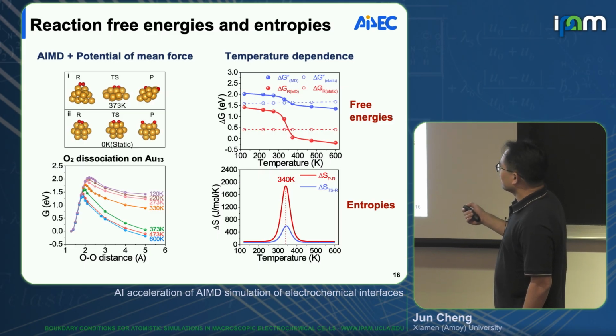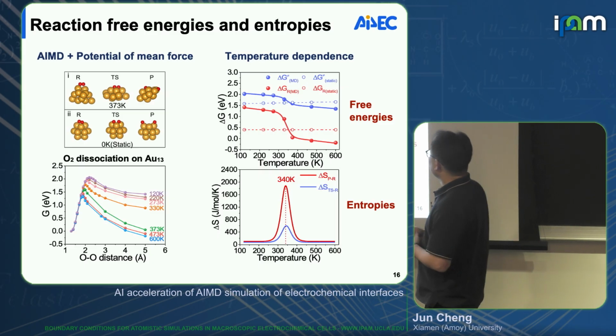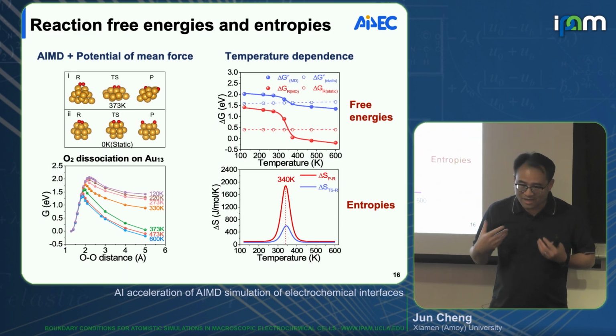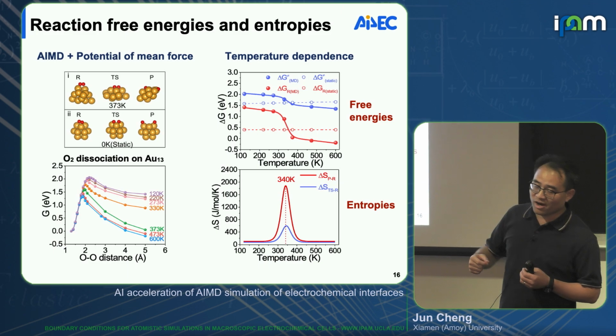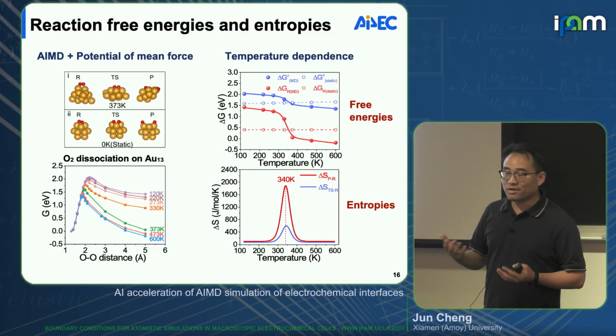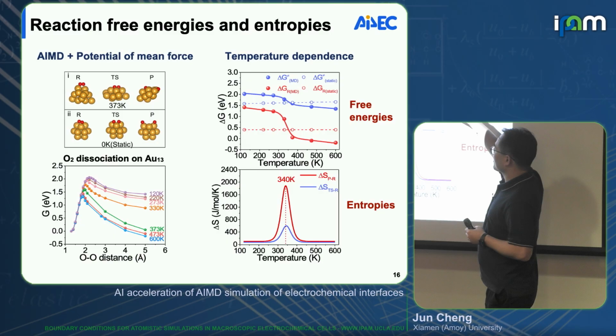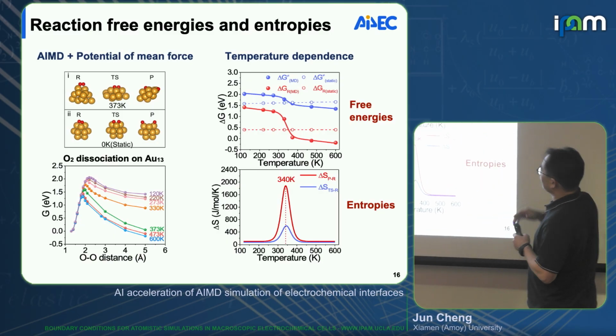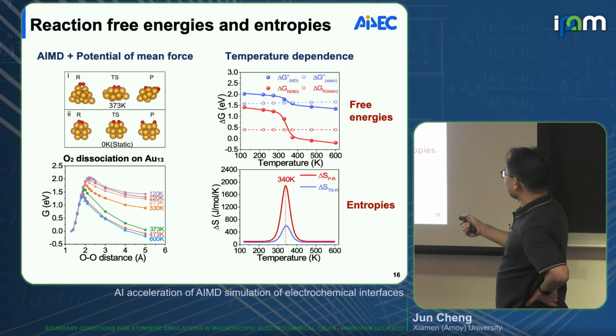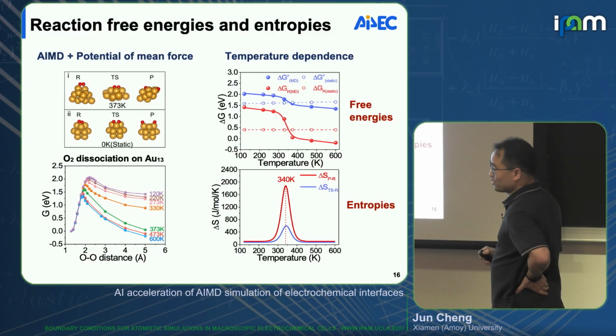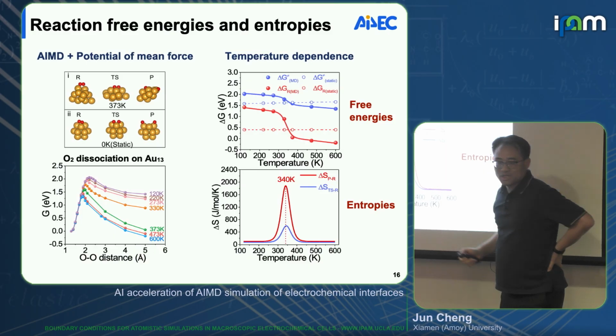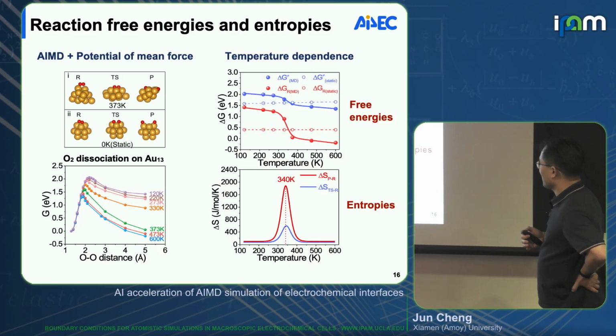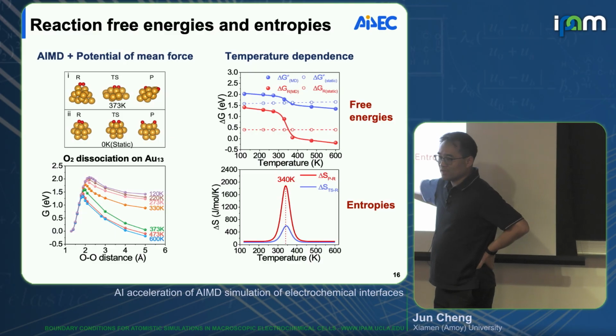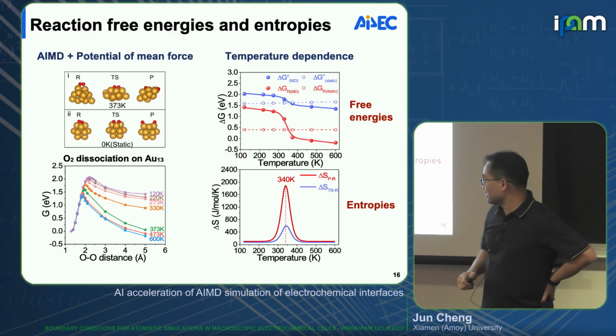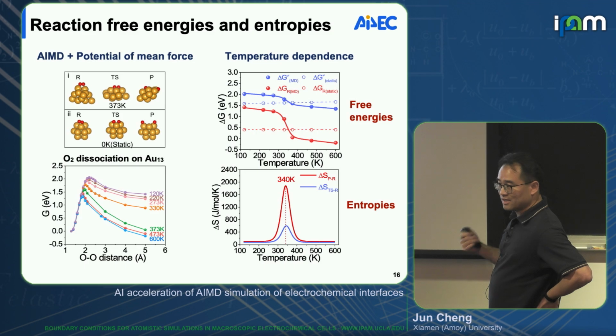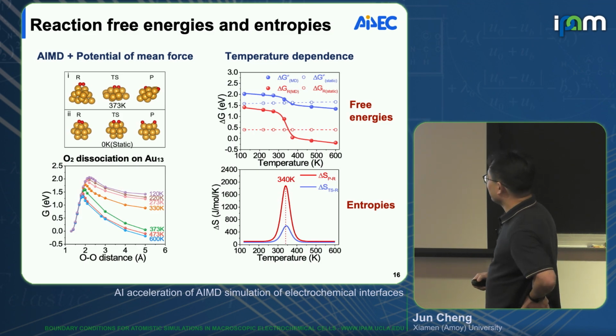This dashed line is actually the standard geometry optimization approach. Then we add on vibrational entropy for corrections. You don't see any strong temperature dependence, right? Low and flat. But if we do the free energy calculation, we see a sudden jump at the intermediate temperature range. Again, take the temperature derivative of the free energy, you get the entropy. So that's the reaction entropy as a function of temperature. You see a huge peak here. So that's a non-trivial entropic effect.